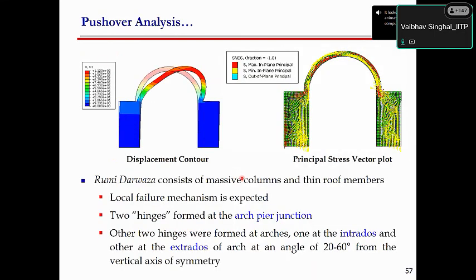And using this pushover analysis, we also identified the possible failure zones. So the 4 hinges have been found out, two at the supports, one at the intrados, one at the extrados. So this is the common failure of an arch. You will need at least 4 hinges for the failure of this system. So these are the 4 locations.